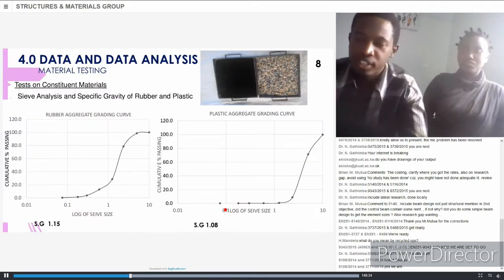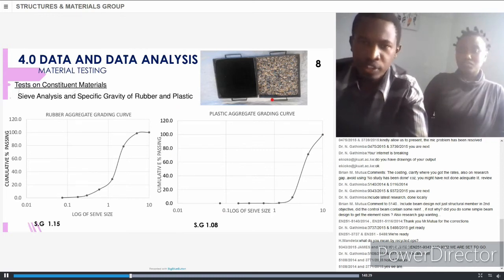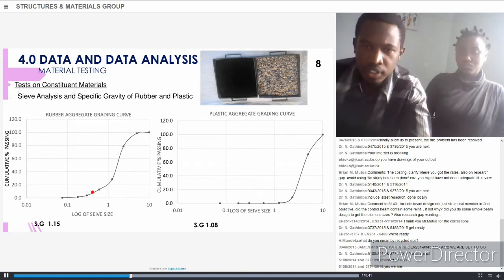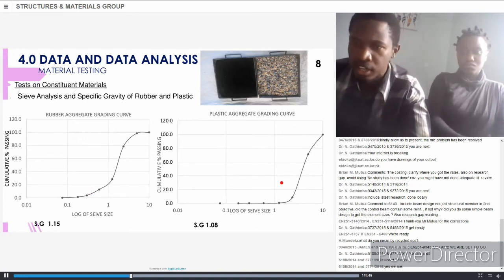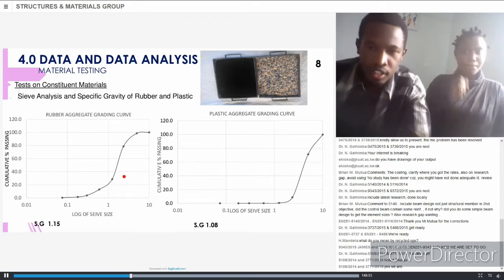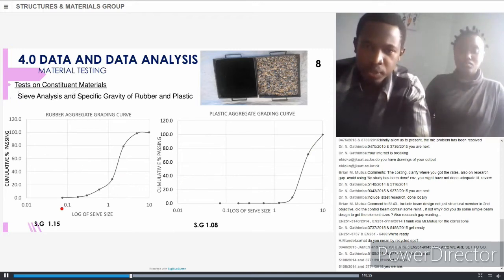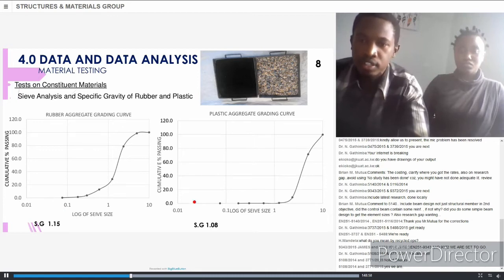Once we obtained our materials from the industrial area, we conducted a sieve analysis and specific gravity of the various particles, rubber particles and plastic particles, so that we can understand the aggregation. The rubber aggregate showed a representation of finer aggregates, whereas the plastic aggregate showed a larger representation of coarser or larger sized particles, and the maximum sieve size was 10 millimeters. The specific gravity of rubber was 1.15, and that of plastic aggregate was 1.08.